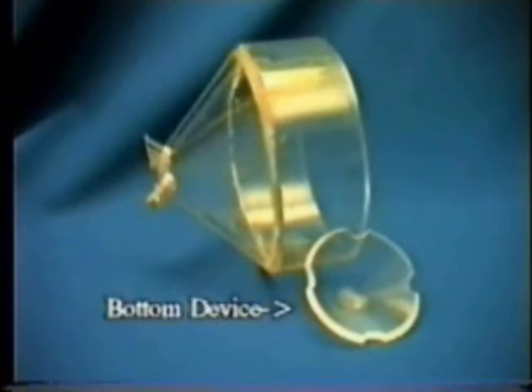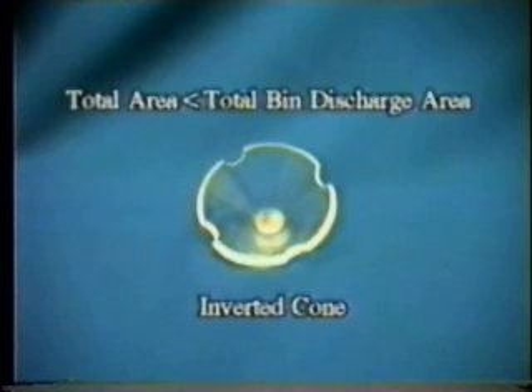First, to the right of the picture, is a bottom device referred to as an inverted cone. The cone has 4 half-circle openings located at equal distances around the circumference of the base of the cone. It's critical that the total area of these openings is less than the total area of the bin discharge opening. That way, sand flowing through these openings will exit without backing up and filling the chamber under the cone.